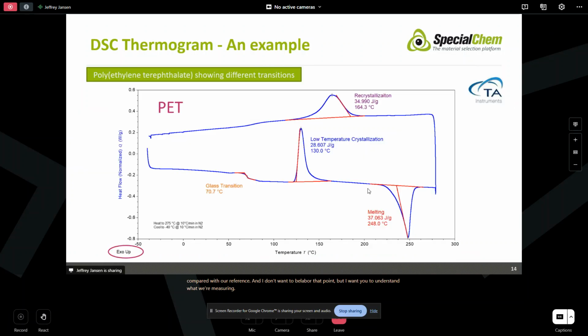What we get is a thermogram. That's what the graph we get from a DSC is called. It shows some of the more prevalent transitions that we might see. This is a sample of polyethylene terephthalate, and as we heat the sample, and we're going to talk more about these experiments later, we undergo a change in heat flow. So we see this S-shaped curve. That's a glass transition. Then as we continue to heat the sample, we're going to form crystals within that PET material, and that's this exothermic transition.